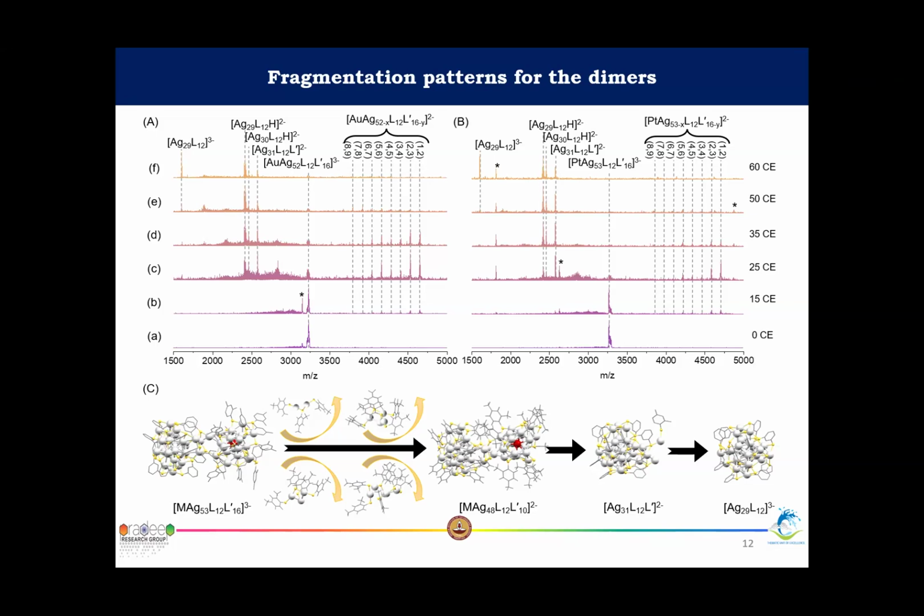Yes, but if you can do silver NMR, even though it's low abundance, careful analysis of the silver NMR can give something. Some people do it. I have read a paper on silver NMR. Deepak, silver NMR would require a lot of sample if you're monitoring a reaction, right? Yeah, that can be the limitation. We have a silver NMR here as well. I was planning to do it, but it requires a lot of sample. Even I planned it for the silver 17 when Swetashree gave it, but it was not observable at that time.